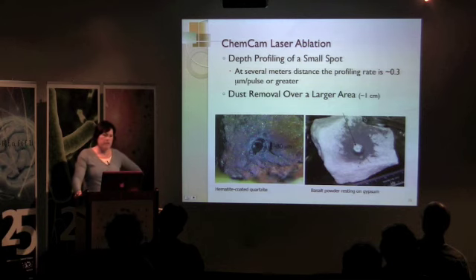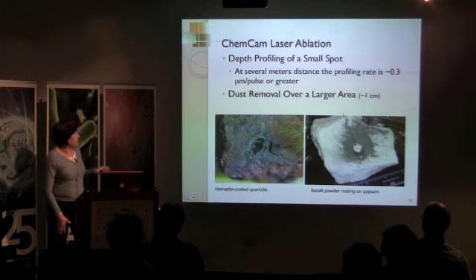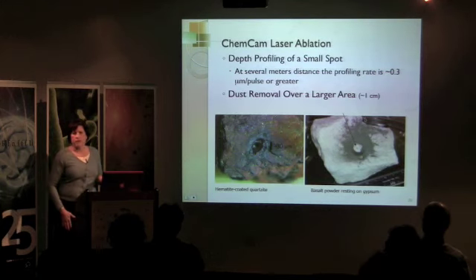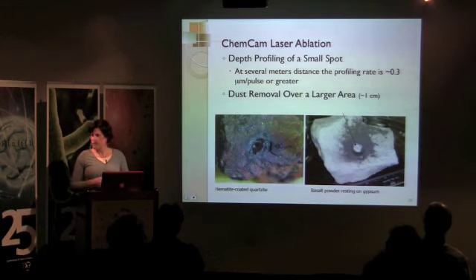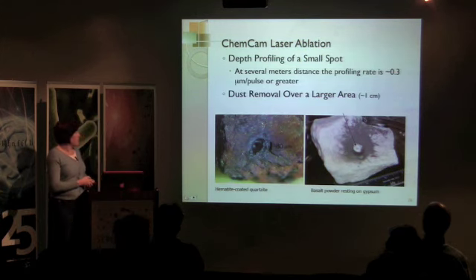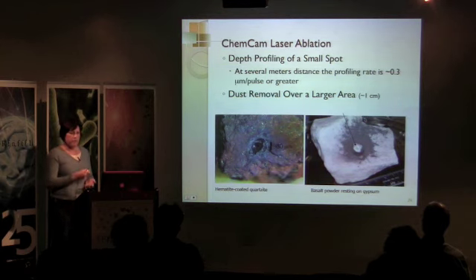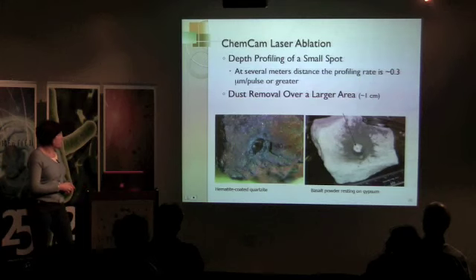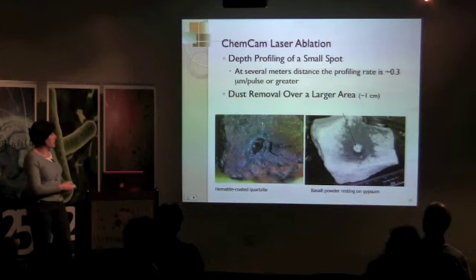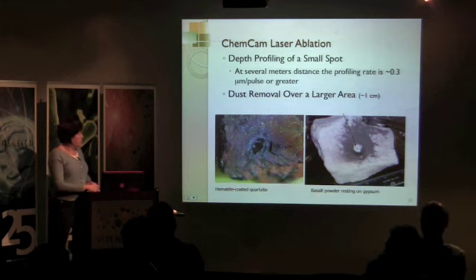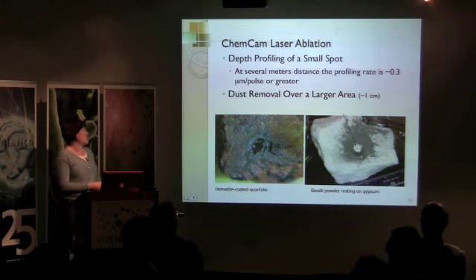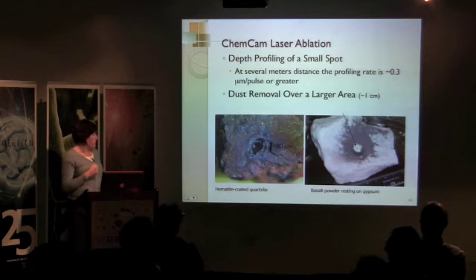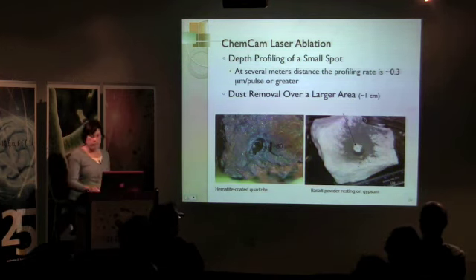Here are some examples showing the ChemCam laser ablation depth profiling of a small spot at several meters away in air. The profiling rate's about 0.3 microns per pulse or greater. So if we pulse somewhere between 10 to 15 times, you can calculate how much we can get removed from the surface. And we can also remove overall dust in a larger area by rastering the laser. And here's an example on the left of hematite-coated quartzite. See this hole of about 500 microns. On the right, we have basalt powder just dumped on top of some gypsum, and then the laser was rastered across the surface to reveal the gypsum, the white substance beneath.